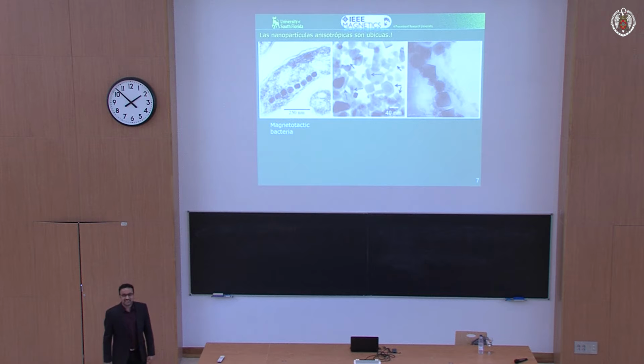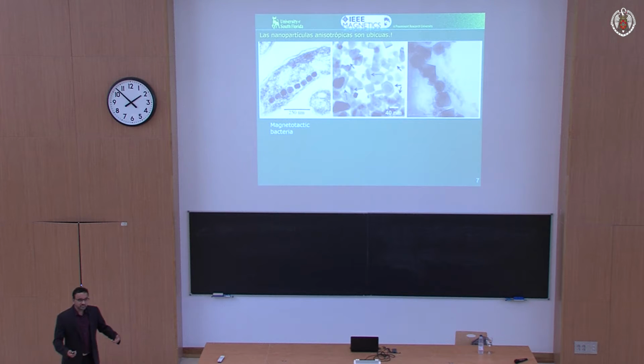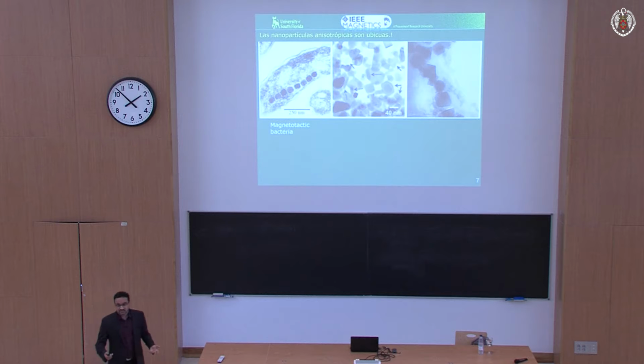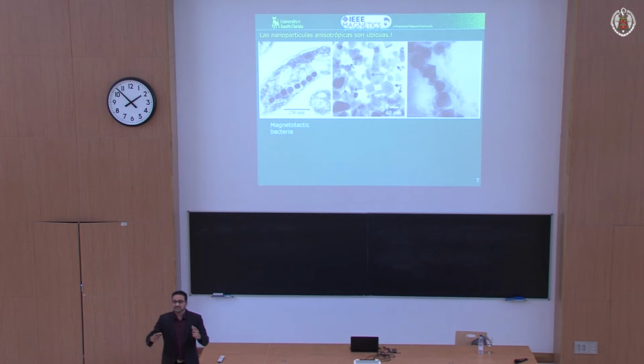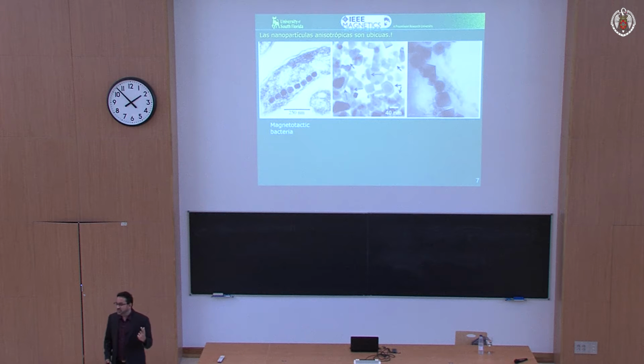So it turns out that these are magnetotactic bacteria. There are some bacteria that produce magnetite or iron oxide nanocrystals, and using dipolar coupling they can make these short chains. And they are making these short chains exactly for the same reason that the Chinese, when they discovered lodestone, found that they can make compasses out of the magnets. So these bacteria are making tiny compasses with nanoparticle chains for the same reason. They want to navigate towards a source of food.